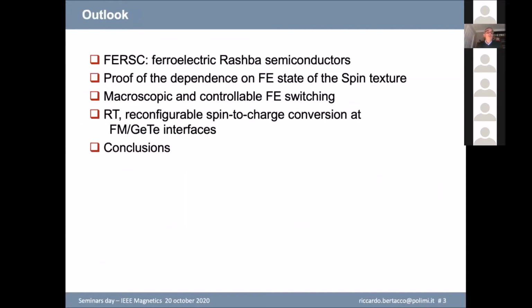I will start by introducing the class of materials named FERSC, ferroelectric Rashba semiconductors. Then I will try to see what the experimental proofs are that they can really work, starting from the proof of concept of the dependence of the spin texture on the ferroelectric state, with a strong relation between the spin and the ferroelectric state of this material. Then the possibility to control the ferroelectric state using a gate in a device, which is not just something you can do with PFM, with an AFM tip, but something that can be applied to a real device. And then, which is the core of this talk, the demonstration that we can really control the spin-to-charge conversion at room temperature at ferromagnet germanium telluride interfaces.